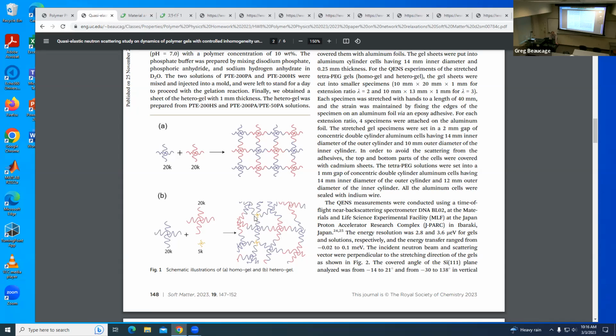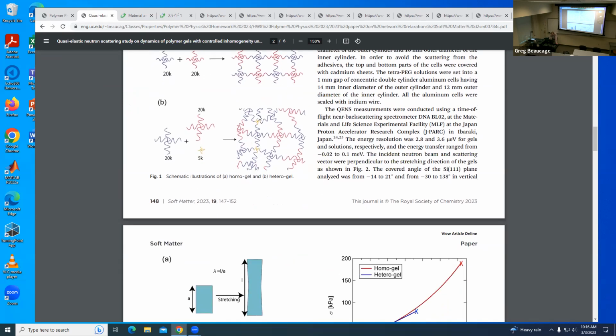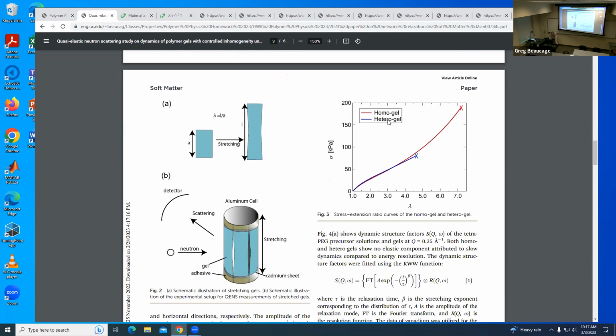So basically, in this paper they're arguing the opposite of that. They make these things, both made as a kind of model system. He has a short chain that he introduces. They're both cross-linked in dilute conditions. And he says the one that's hetero, with the short and long, breaks first. The one that's homo stretches further. Its extension at failure is like 7 times.